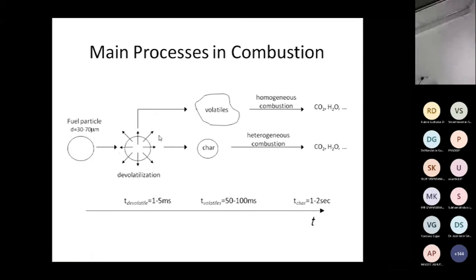So in the fuel particle, first is devolatilization, where volatile is removed. It takes some milliseconds. Once volatile is removed, the balance is char. Volatile gives you homogeneous combustion. Then char is a solid, so you have heterogeneous combustion. The volatile matter combustion will take a few milliseconds, whereas the heterogeneous combustion of the char particle will take 1 to 2 seconds. Among these two processes, this is a very slow process, because volatile is nothing but a gas, so homogeneous gas combustion is at a much faster rate. Char takes a few seconds, at a slower heating rate.